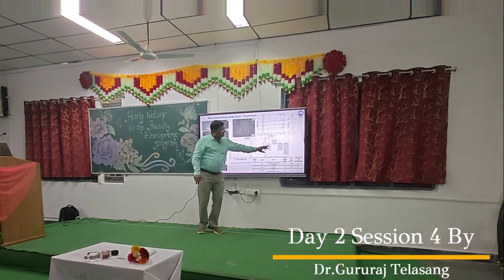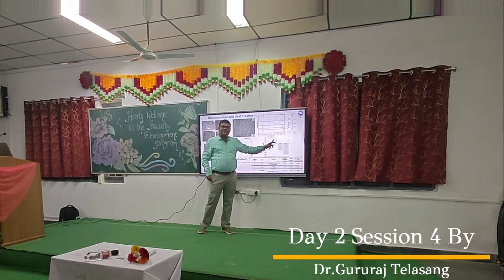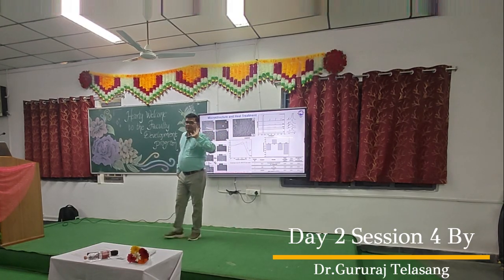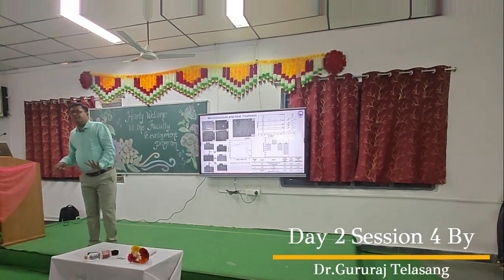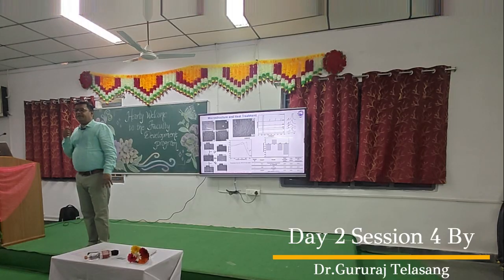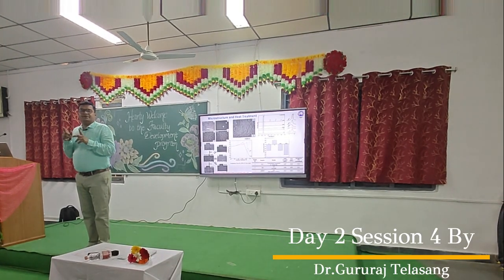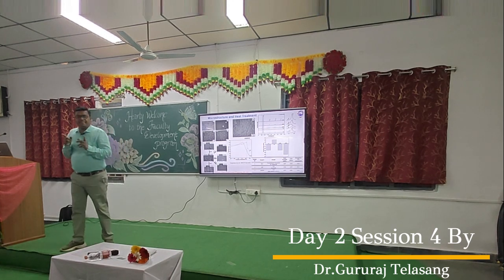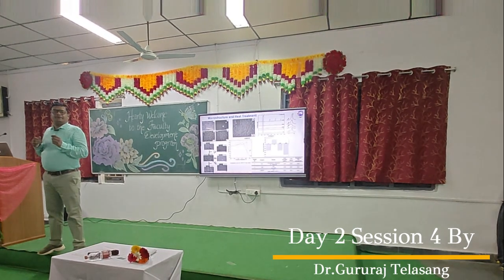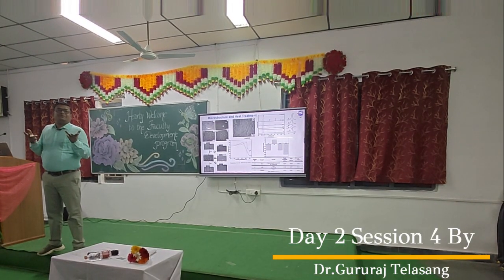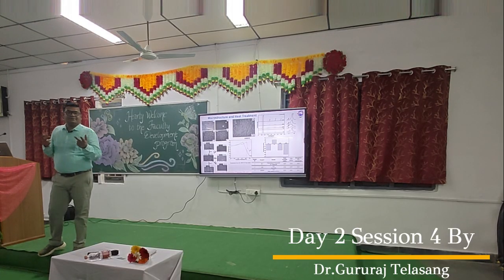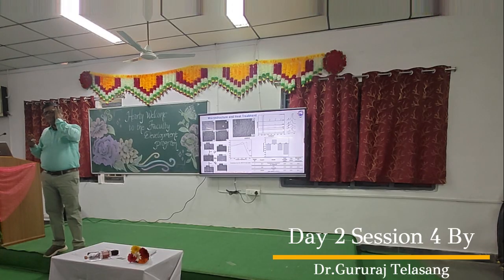So we do XRD, we measure residual stress. Can you see the as-built has tensile residual stress? Do you know residual stress? You know tensile and compressive residual stress. You know peening. Shot peening. You know shot peening. What is that? Bombarding with balls. Why do you do that? To improve the property. What property? Surface property. What surface property? Just like hardness? Hardness maybe, depending upon the material, but the purpose is different. Hardening the structure? Yes, but it will affect what ultimately? It will not alter the structure, but to some extent, yes, I can't deny that.